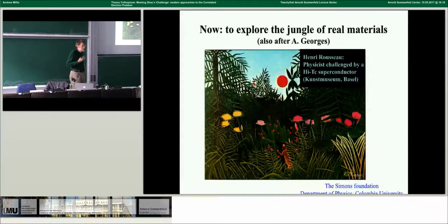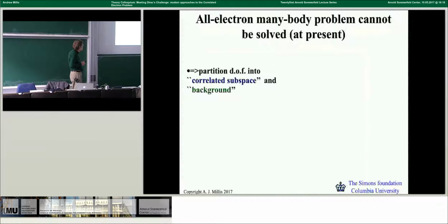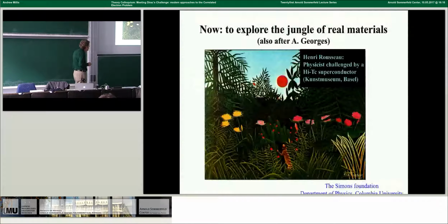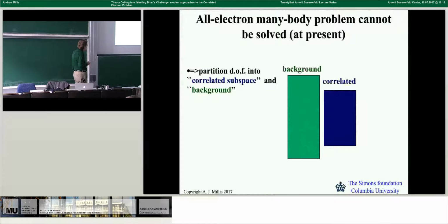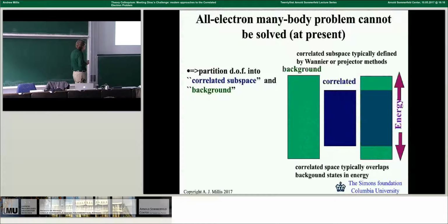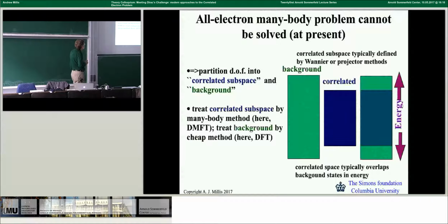All right? So the issue which is nicely expressed by this is how do we take our insights from simple models and navigate through the jungle, as you might call it, of real materials? So again, this jungle is too complicated to deal with directly in most cases. So what we do is, in one way or another, take all the degrees of freedom and partition them into a correlated subspace and a background. Typically, you can define the correlated subspace by picking out orbitals that you like. There are technical ways to do this that go by the name of maximally localized Wannier functions or projection methods. Right? You treat the correlated subspace by some kind of many-body method. You treat the background by a cheap method, and you do some kind of self-consistent embedding.